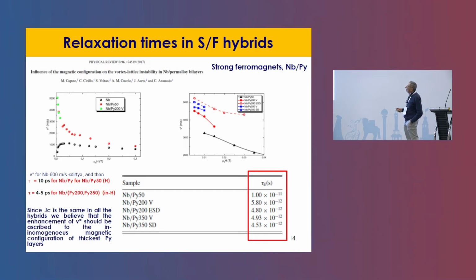The red points are when the sample is in the homogeneous state, and here is when stripes are created in the system. And you can see that you have an increase of the critical velocity, so a decrease of the relaxation time, which is clearly related to the inhomogeneous nature of the magnetic configuration, because since JC is the same in all the hybrids, we ascribe this behavior to the different magnetic configuration, which here is homogeneous, and here is inhomogeneous. And you can see here that we have a relaxation time of the order of a few picoseconds.